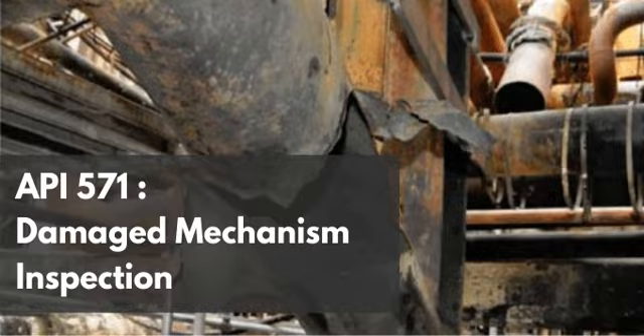But, and this is crucial, 1175 degrees is specifically chosen because it remains safely below the lower critical temperature of carbon steel, known as the A1 transformation line. Because if you were to heat the steel to 1350 or 1400 degrees Fahrenheit, the BCC ferritic or pearlitic microstructure would begin to transform into austenite.